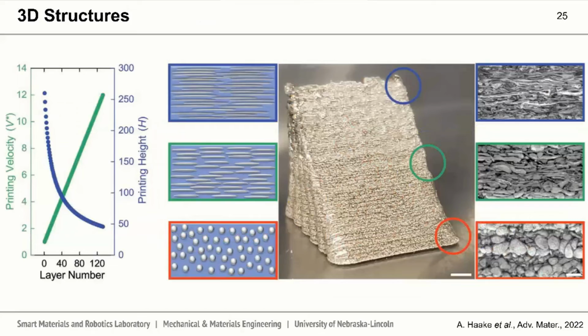We can expand this from 2D to 3D structures, where we begin to tailor the printing parameters, the normalized velocity as a function, and printing height for each layer in our composite. This allows us to create layers with spherical droplets on the bottom all the way to highly elongated inclusions on the top of this prismatic triangle.